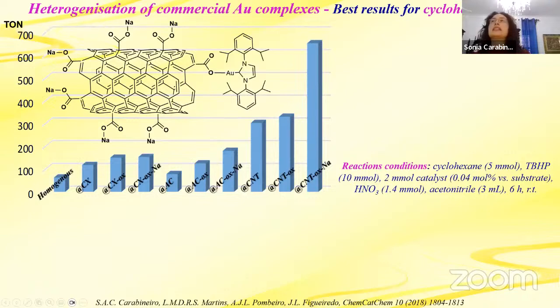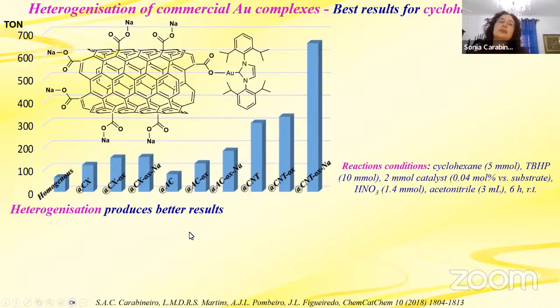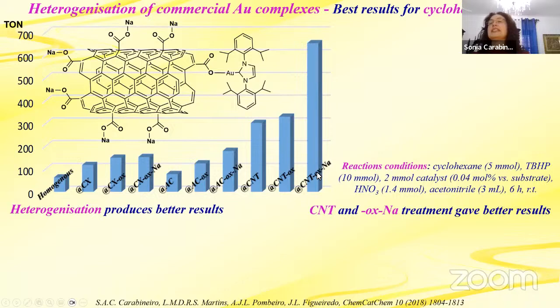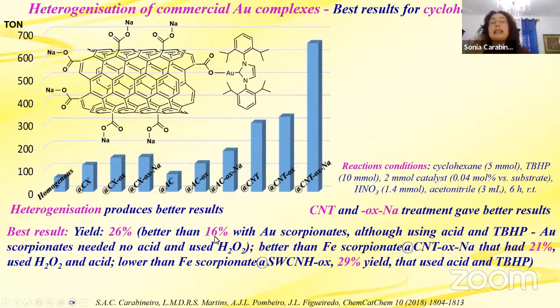So the heterogenization results for cyclohexane oxidation, see here we have homogeneous, and if we anchor on carbon support, see the best result is there, heterogenization is better. And again, carbon nanotubes, and this oxidizing treatment gives the better results, and the best results were obtained with this complex that is drawn there. And the best result was 26% yield. Of course, it's better than the 16% with gold scorpionates.